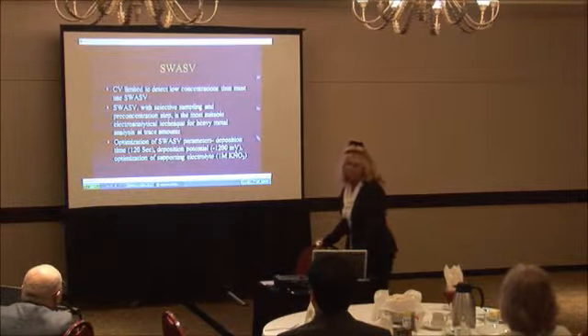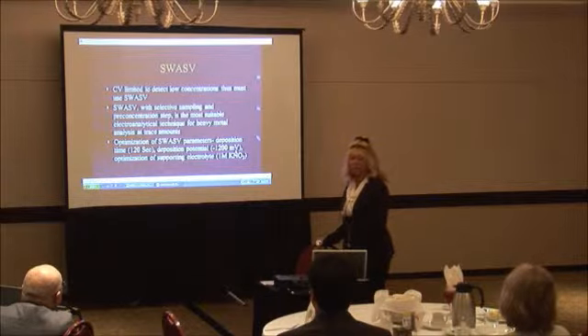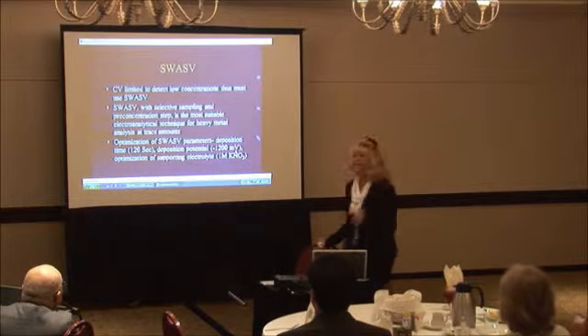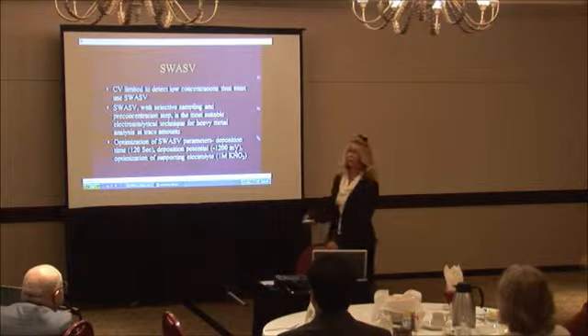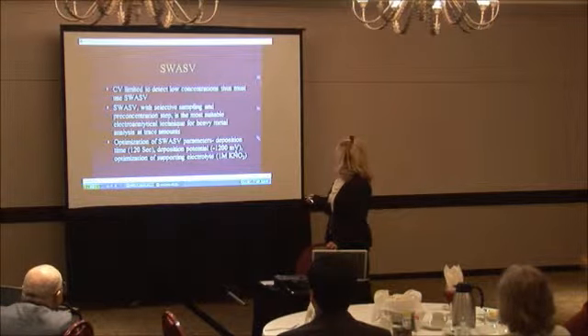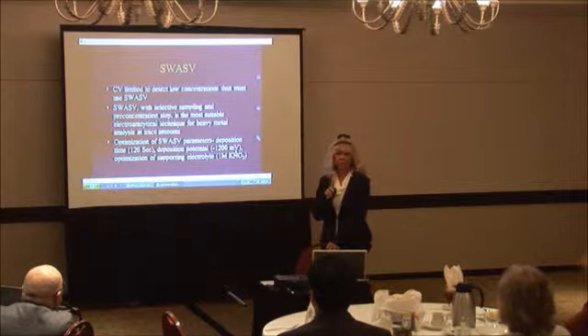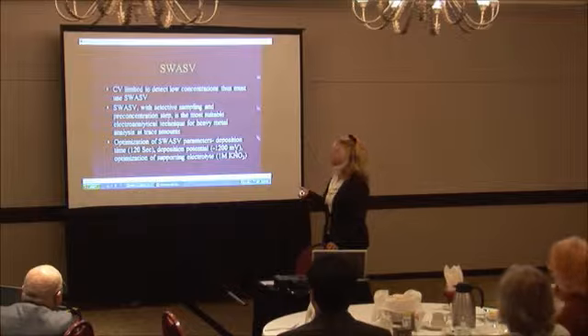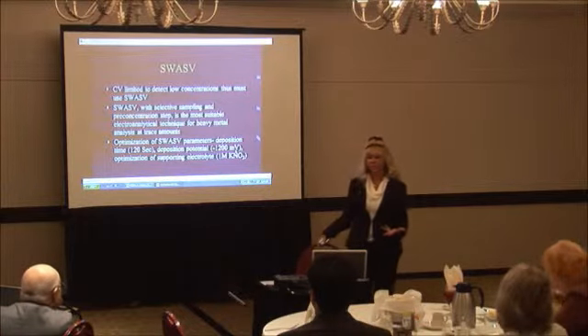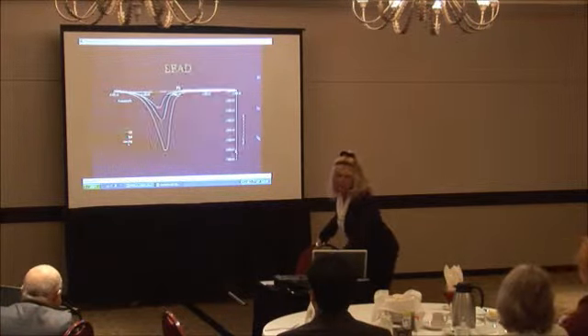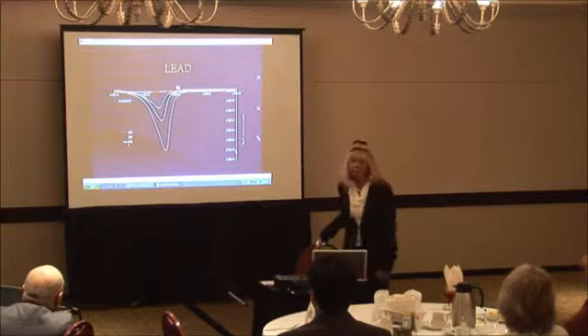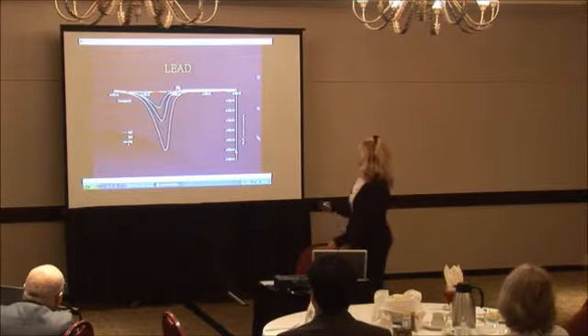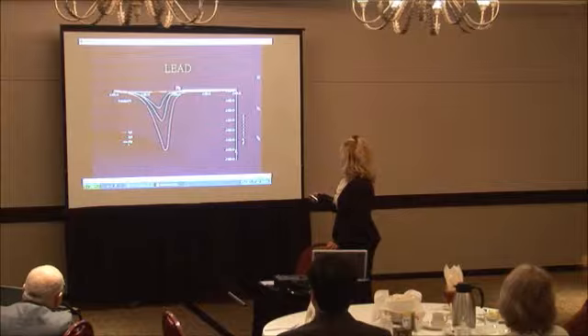So I'm going to show you square wave anodic stripping voltammetry, they had to play around with the parameters. It is software compatible. So they had to look at, was this the best deposition time? So they had to do many trials. I'm only showing you the optimum results. Many trials to figure out what was the best way to detect with square wave anodic stripping voltammetry for these electrodes built. So here's square wave anodic stripping voltammetry, and what's so neat is you can see that you can get 1 part per billion, 5 part per billion, and 10 part per billion.